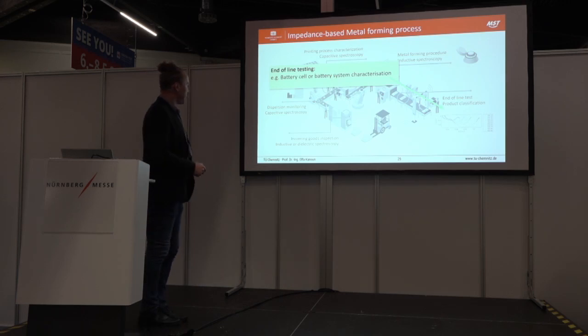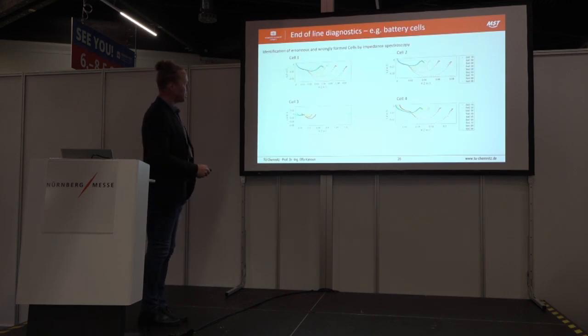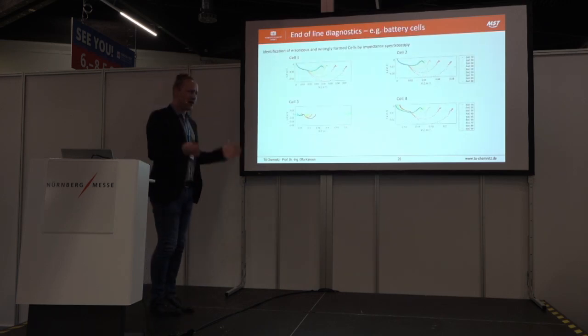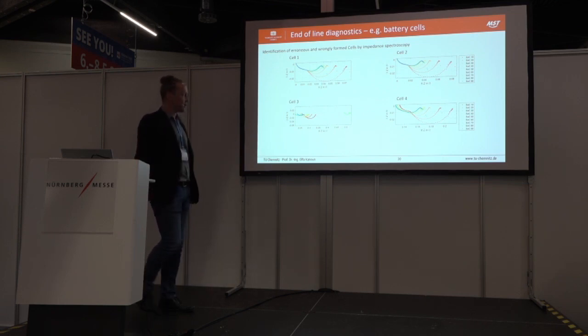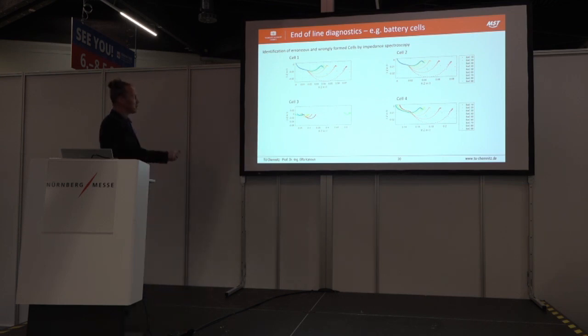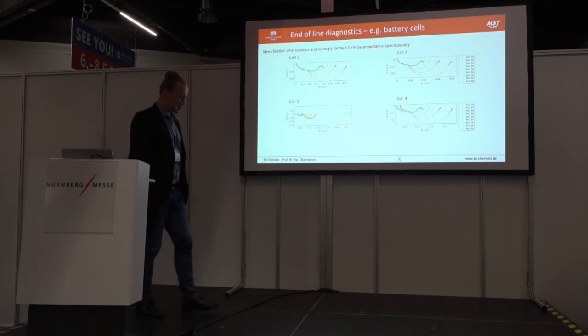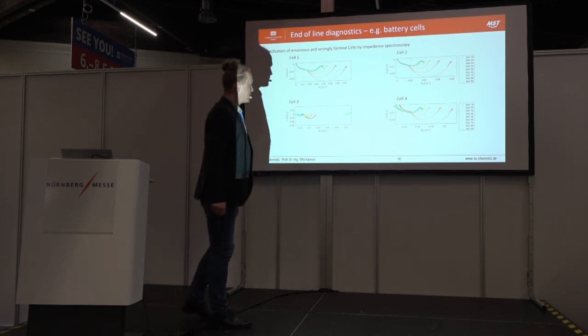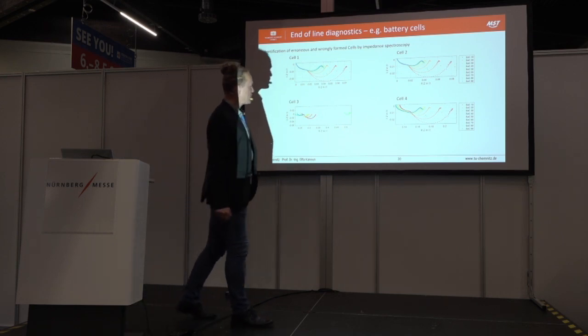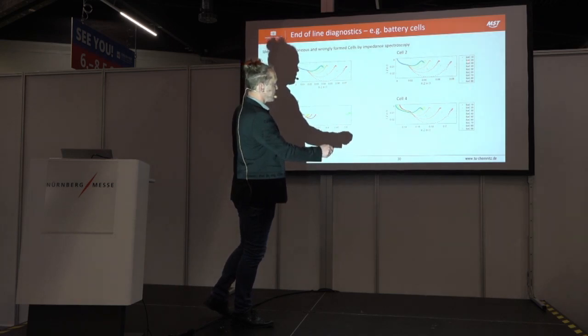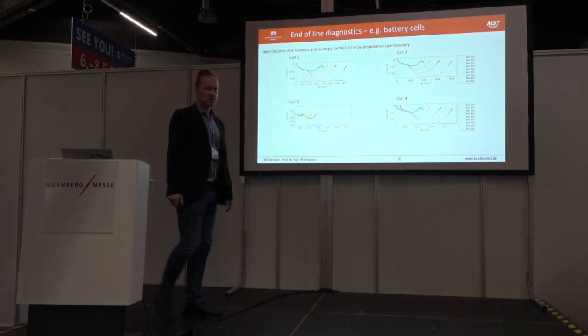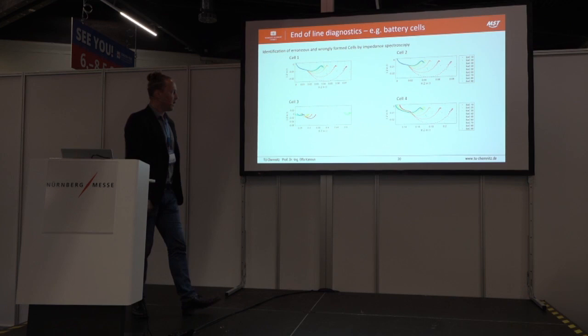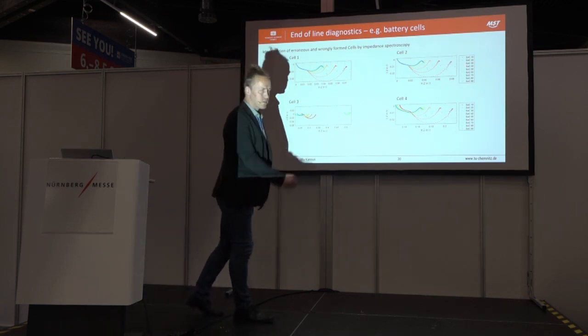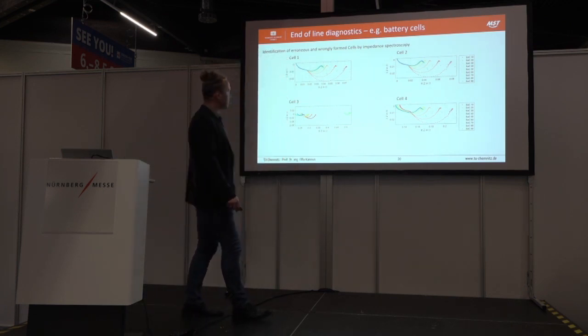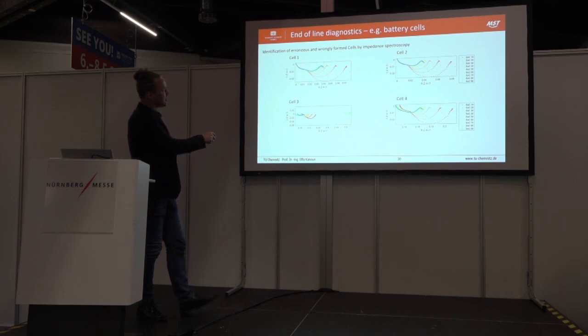So, end of line testing. I like to always use the battery as my device under test. Here you can see such a comparison study of 4 different cells. So to explain this measurement, you see here the 9 different stages of the SOC of a battery. And in each stage, we made the impedance spectra of the cell. So you see the typical increase of the curve by charging.